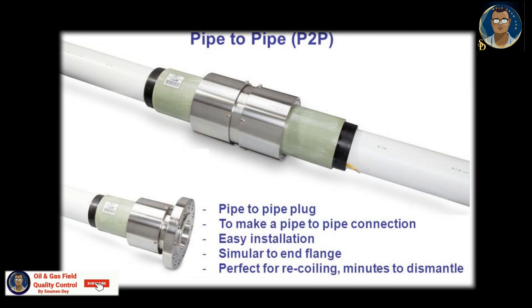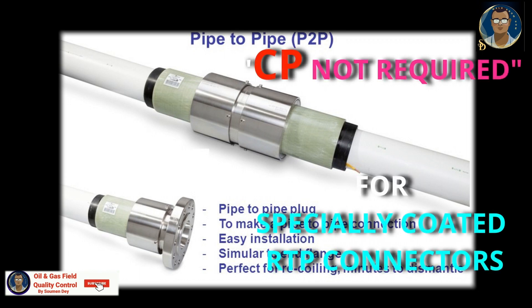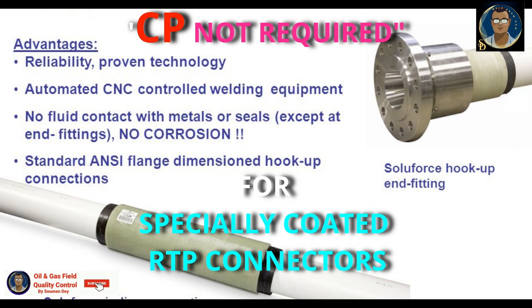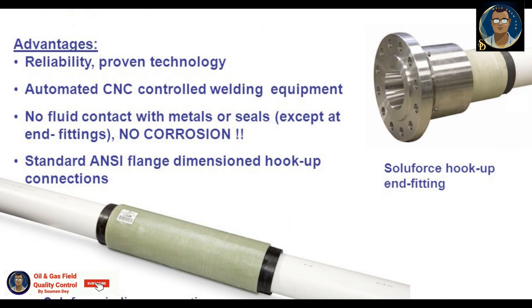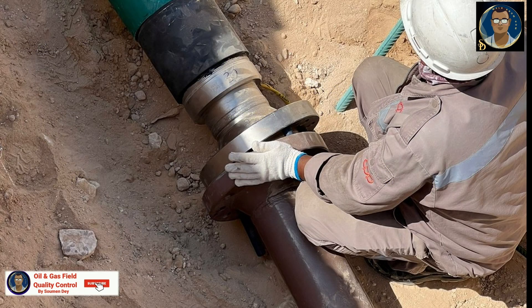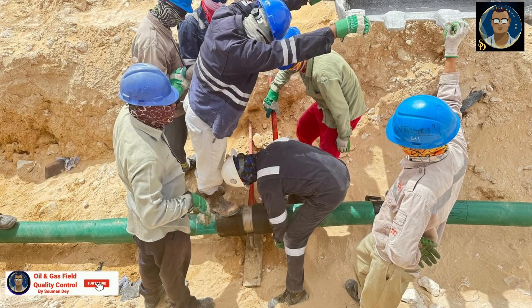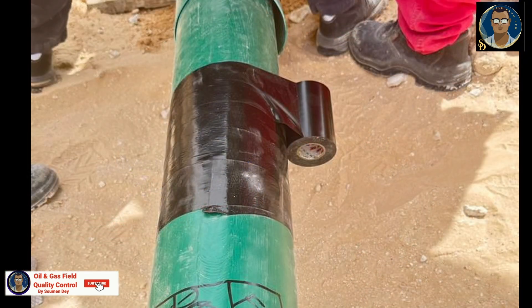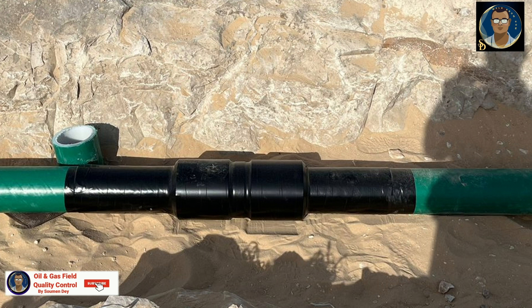Now I will share my experience from our RTP pipeline. We got manufacturer confirmation that cathodic protection is not required for specially coated RTP fittings, which avoided a lot of complications, expenses, and time for us as a contractor. RTP connectors are supplied as carbon steel with special electroless nickel coating, abbreviated as ENC, for corrosion protection of fluid-exposed or wetted parts. The ENC coating is as per ASTM B733 with SC4 deposit for severe service rating. All external parts are supplied with a zinc phosphate coating for external corrosion protection from soil, water, etc. All connectors are further wrapped with Polyken tape after installation for additional protection against external corrosion. So cathodic protection is not needed for connectors before or after installation in our case.